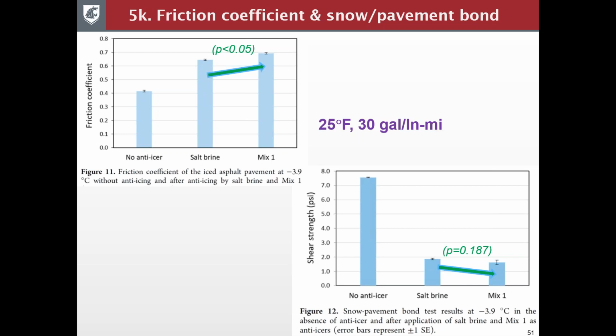And also we test the shear strength of the snow bonding to pavement. And there's a little bit lower bond strength with the mix 1 anti-icer on pavement, which means it's beneficial. Again, in this case, the p-value is not as good as 0.05, but it still gives us roughly 82% confidence that mix 1 is better in terms of anti-icing.